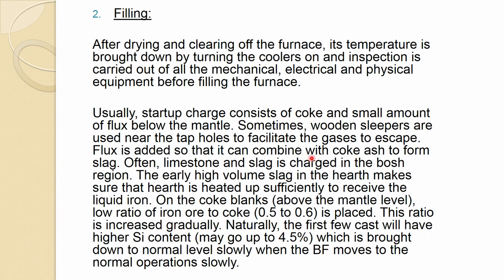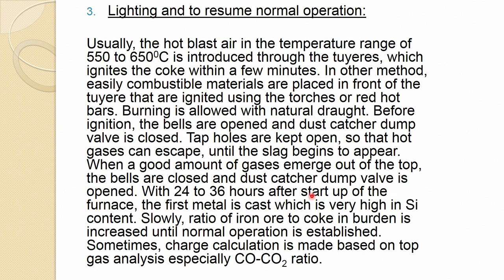This is the filling process after drying is done in the blast furnace. After the furnace is packed with ore and other things, comes the lighting step. Usually hot blast air in the temperature range of 550 to 650°C is introduced through the tuyeres, which ignites the coke within a few minutes. When injecting that high-temperature blast air, the coke will ignite very soon.